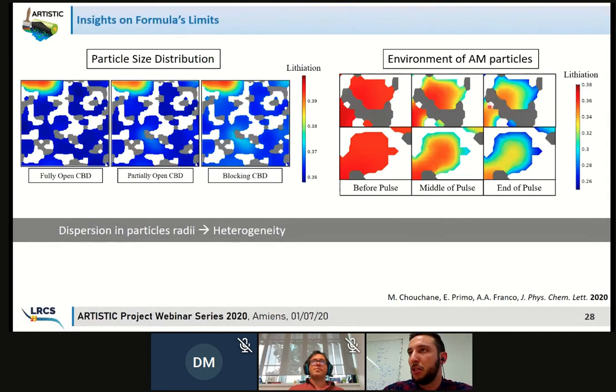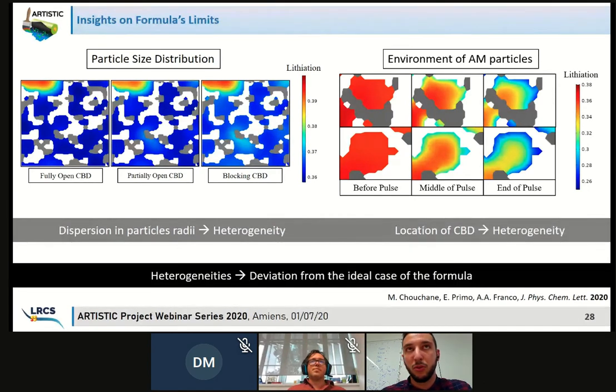And due to this CBD preventing access of lithium, of the intercalation, you can see that in this particle, which is not fully covered with electrolyte, you have a stronger gradient than in this particle, which is fully in contact with electrolyte. So this led us to think that this location of CBD was also a source of heterogeneity in our system. So more or less, we've shown that these two are sources of heterogeneity, and these heterogeneities are going to lead to the main source of deviation from this ideal case where the formula was derived.